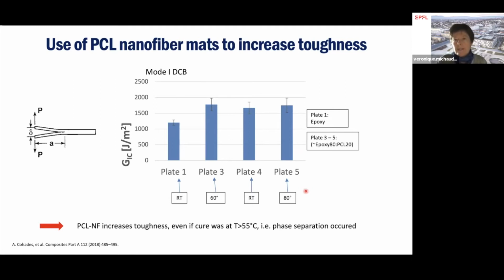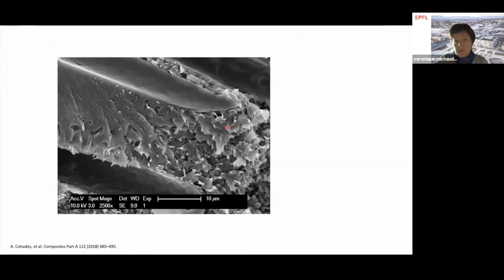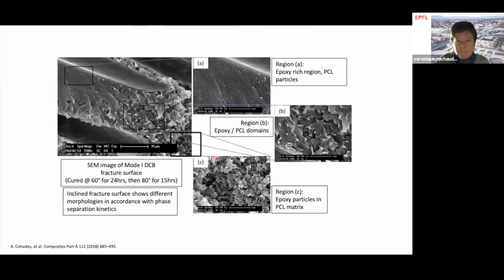So we had melting and phase separation, which we could actually see in this SEM picture. You see that this is the matrix. You see a lot of different things happening. But if we look a bit more carefully, in some regions, you see that you have an epoxy-rich region with a bit of PCL particles. In other regions, you have a phase separated domain. And then in the final region, you have epoxy particles clearly visible in the matrix, showing that we have this phase separated morphology we were looking after. So we get a good toughness improvement.